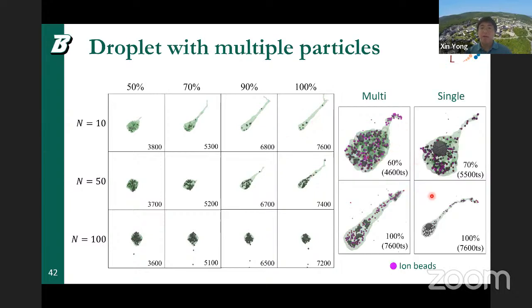So if you directly compare multi with single, you can see that there are some subtle changes between these two dynamics. The single case is less homogeneous, and you get more of a tadpole shape, while for the multi one, because the viscosity change is much more homogeneous, you get a better nanowire formation.